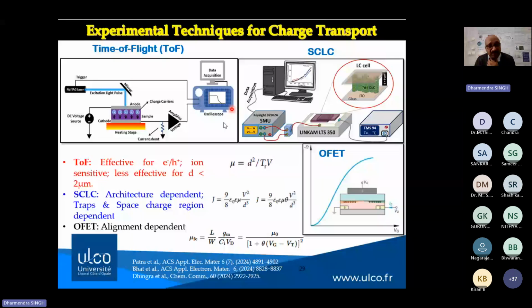Obviously, SCLC is an architecture-dependent technique, in which you need two devices to form, and sometimes the fabrication is quite complicated. These devices often suffer from traps and space charge regions. When your material or devices are full of traps, either shallow traps or deep traps, then you have to do a correction in the Mott-Gurney equation, and without correction you will not get the equivalent current. OFET is a very nice technique as well.